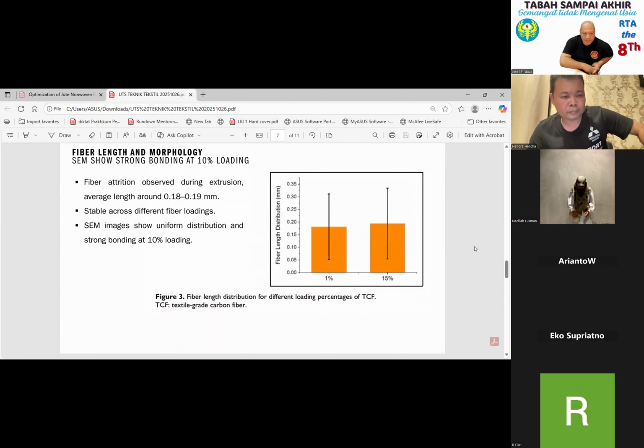It is about fiber length and morphology itself. So let's take a closer look at the fiber structure and morphology, because how the fiber behaves inside the polymer matrix plays a huge role in the final composite performance. During the twin screw extrusion process, the carbon fiber experiences mechanical shear and friction as it mixes with the molten polypropylene. This can shorten the fiber, a process called fiber attrition.